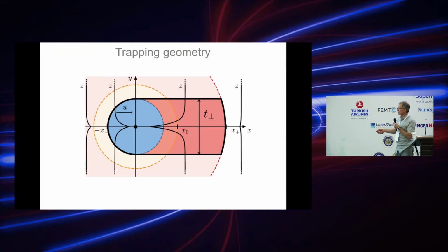Here you have this curved line, that's the Z direction, and X direction, and away from the pin the vortex is only a little bit curved. Then when it comes, it jumps to the defect, and it gets this kind of tip of the vortex which sits on the defect. We move it further, but the tip continues to sit on the defect, and eventually there is a jump back to the unpinned state.